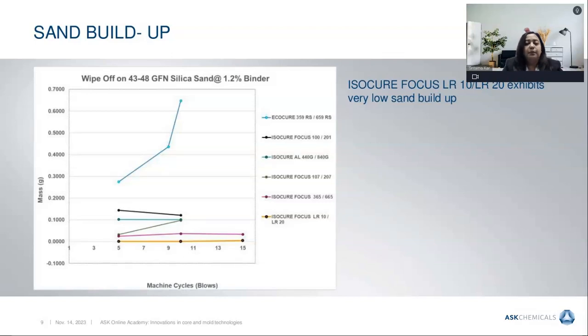As we can see in this plot, for most of our binders, we noticed a buildup after 5 or 10 blows, and some of the binder systems have pretty high sand buildup. But for Isocure LR10, LR20, which is the bottom curve, there is zero sand buildup till 15 blows. So this lab data was a very good indication of how this product is supposed to perform in the field.